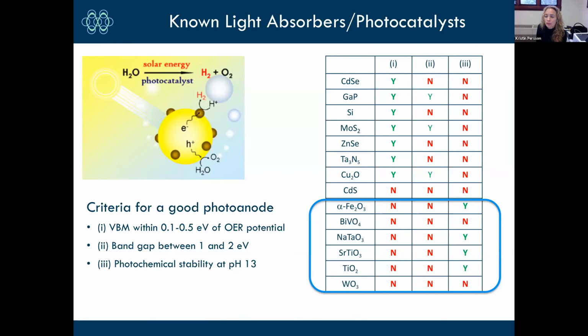And to find a good photoanode, we need a couple of criteria, so again, links in that chain, right? We need a valence band maximum that is close to the oxygen evolution potential. We need a band gap that can absorb the majority of visible light, so somewhere between 1 to 2 eV. And we need photochemical stability.